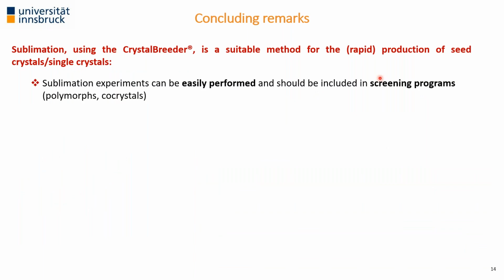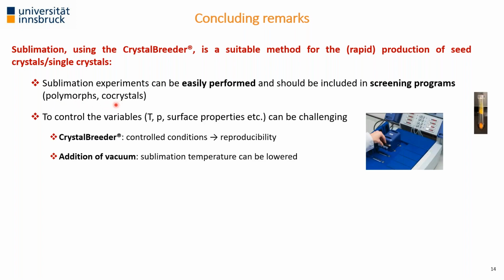So I hope I could show you the sublimation can be easily performed. And in my opinion, it should be included in screening programs, especially if you're looking for different polymorphic forms, but also for co-crystal. What can be extremely tricky when you do sublimation experiments is to control the variables, especially temperature and pressure. If you have equipment, like for example, the crystal breeder, this can be easily done. What else? You could modify surface properties, onto which surface you are doing a sublimation experiment. So you have more variables than I've shown you. And yeah, with instruments like the breeder, you can easily control the condition. They're highly reproducible. And the ability to reduce the pressure is really valuable if you're performing sublimation experiments, because then for certain compounds, you may be able to do sublimation experiments, which otherwise you couldn't be doing.